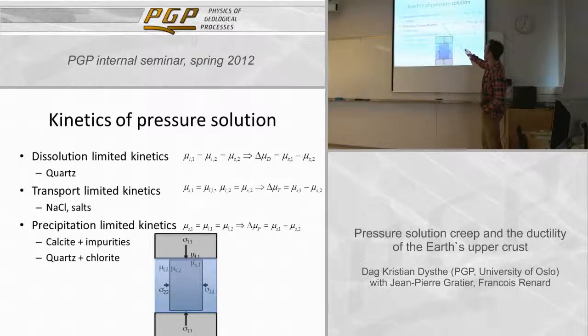Now, in looking at this three-step process, we can say the important thing is this dissolution step. What is limiting the rate is the dissolution step. Everything else has time to equilibrate, so all the other chemical potentials are the same, and the driving force for the dissolution is in fact the total difference in chemical potential from there to there.